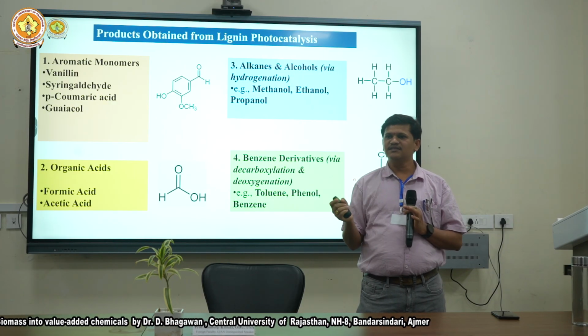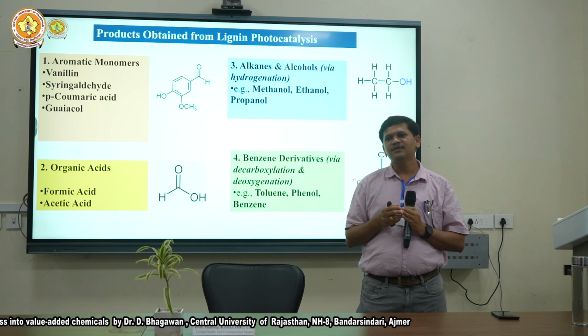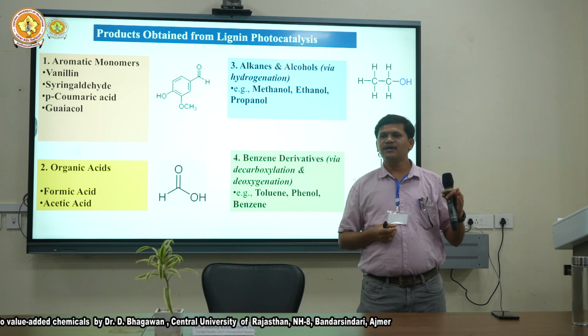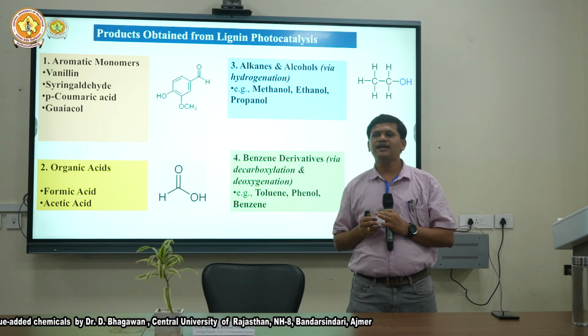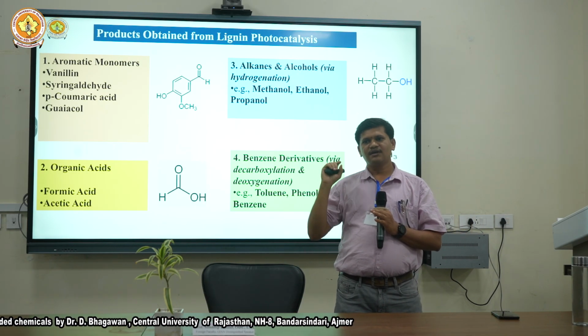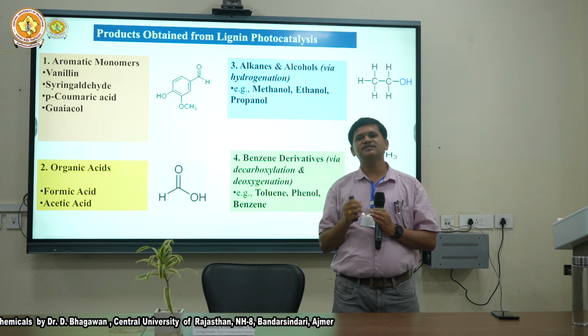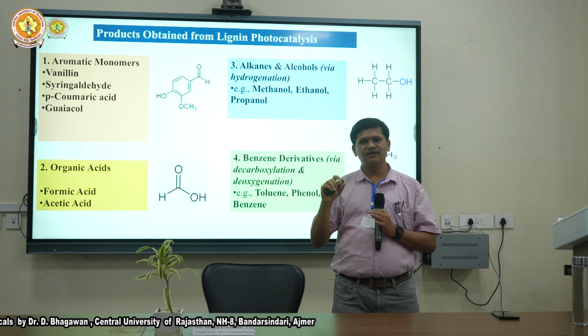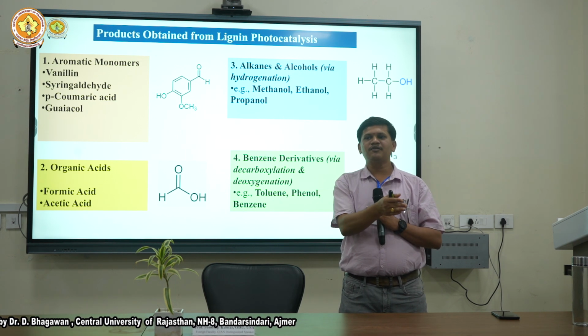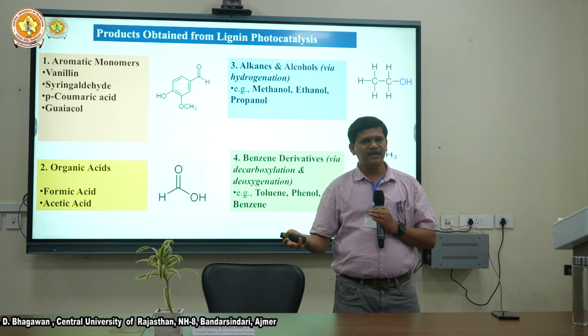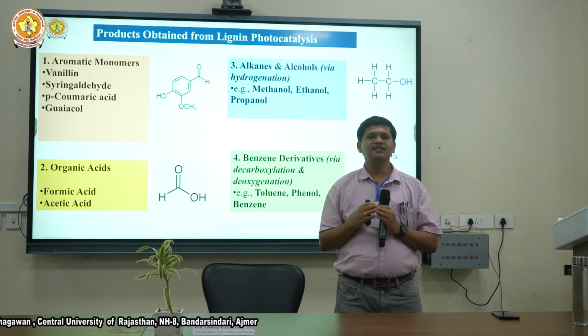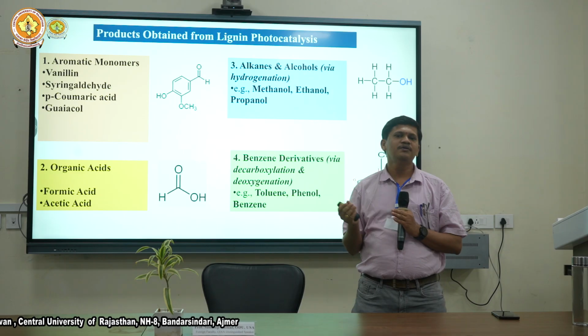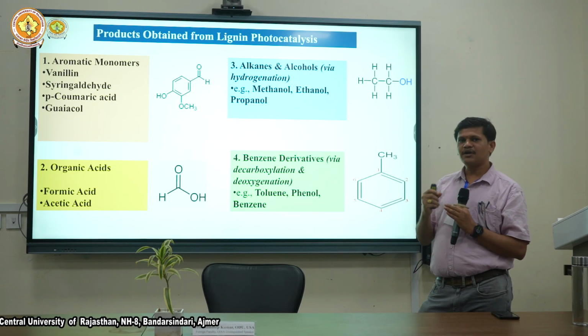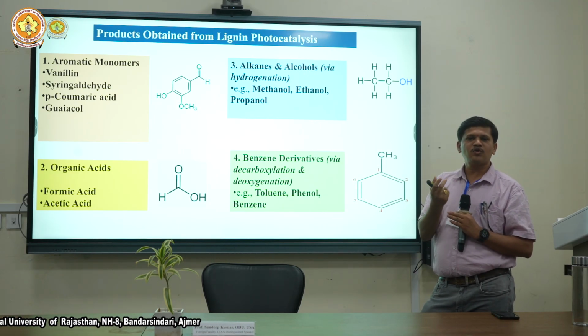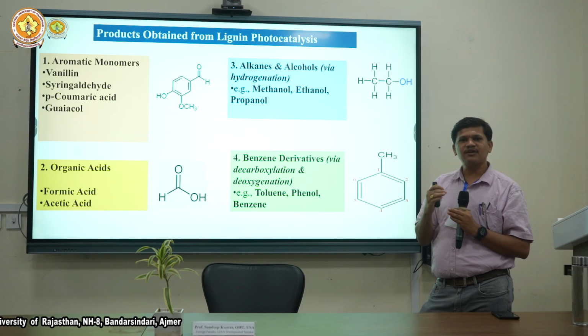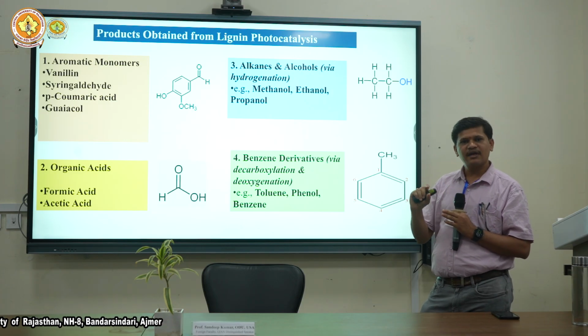Like, it will change. So because of that, titanium, it's the longest one and the older one, we are still depending on titanium, because of the characteristics of titanium, every synthesis is going to change. Whenever you change the precursor, whenever we go for different controlled or operational conditions, obviously the character of that catalyst is going to vary. So it is better to have more catalyst from the same batch, so that we can process the same catalyst for n number of samples.